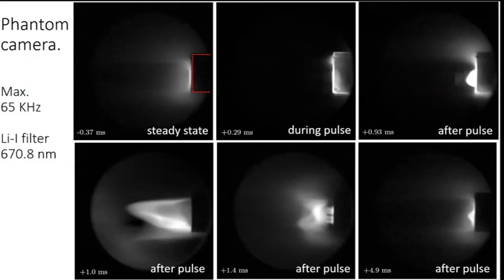We have fantastic measurements, really beautiful images, I think, of what happens during a pulse. So you can see from left to right and from top to bottom what's happening in chronological order. In steady state, you see the target outline in red, and there's a white lithium cloud. That's because it's just a black and white image right in front of the target. And then during a pulse, suddenly we get this bright layer of light wrapped around the target. And you can see after the pulse that this layer expands rapidly. It expands really fast. So it appeared that there was, in fact, some sort of compressed high-density vapor layer,